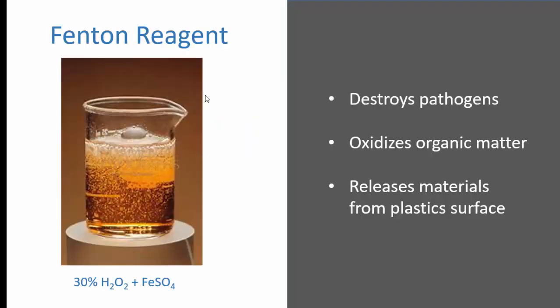Our final method selection uses those three key features that we found common to most analytical methods, but in a slightly different order. We chose as our first stage to do the wet oxidation. Almost 90% of the research articles use some form of wet oxidation, and we find that extremely valuable because, for one, it oxidizes a lot of the organic matter and the easily oxidizable carbon, and so it's a form of disinfecting the sample and protecting the laboratory staff before moving forward.